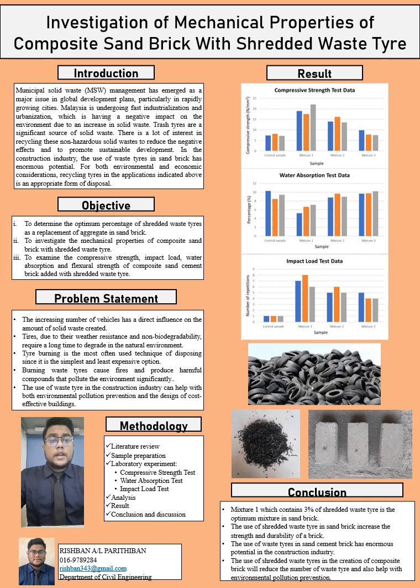As a conclusion, in a nutshell, the goal of research is successfully achieved. Laboratory experiment test shows that mixture 1, which contains 3% of shredded waste tire, is the optimal mixture in sand brick. From this proposed method, the use of shredded waste tire in sand brick will eventually increase the strength and the durability of a brick. Laboratory tests prove that the use of waste tire in sand brick has enormous potential in the construction industry. As a consequence, the use of shredded waste tire in the creation of composite brick will reduce the number of waste tires and also help with environmental pollution prevention.